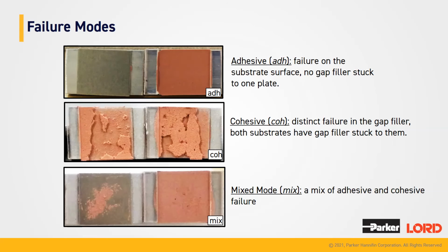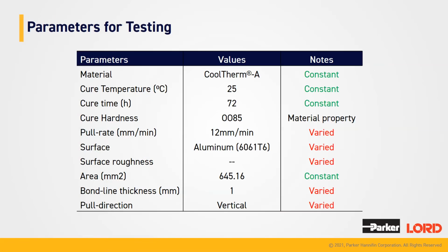And then also to define failure modes for the upcoming study, we have 3 different modes we'll be seeing. The first is adhesive failure, which is the picture in the top here, where you can see that one substrate does not have any gap filler and the other one has all of the gap filler. Moving to the middle picture, you see cohesive failure, which is where both substrates have gap filler stuck to them. And then finally, we have mixed mode, which is the bottom picture, where you can see kind of a mix of adhesive and cohesive failure. And then you can see here our parameters for testing, as well as what we've kept constant and what we've varied. And of course, we'll explore this more in the coming slides.